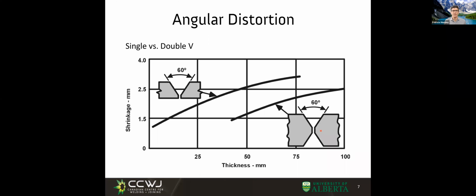We're working on doing this more rigorously. But this is what happens. Let's say I weld it and I flip it, and this part is welded, and it would have a distortion comparable with what is to be expected from a single V. Now I'm going to do my new weld, but guess what? I'm doing it in an already different starting condition than before. And in addition, there might even be some residual stresses involved in some cases. So it's never exactly the same. It's not the same to start with a 60-degree V as it is if I did the weld on the backside before; chances are that this opening is bigger than 60 degrees. Very interesting. So that is comparing a single V with double V. Double V, because of symmetry, will give you less angular distortion.